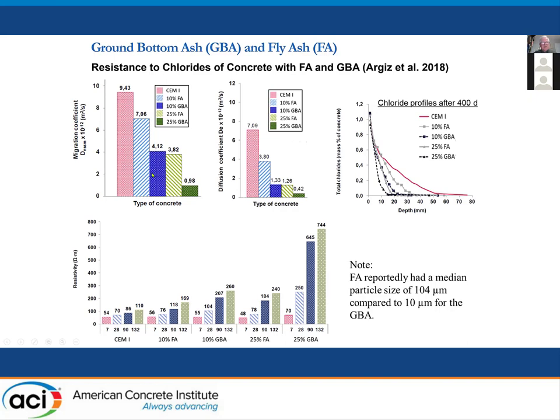In this case, the 10% bottom ash performed better than the 10% fly ash, and same at 25% with this particular source. And you can see the chloride profiles, the ground bottom ash had much better resistance to chloride penetration. Similar trend with resistivity, the bulk resistivity measurements, if you like that better than migration.